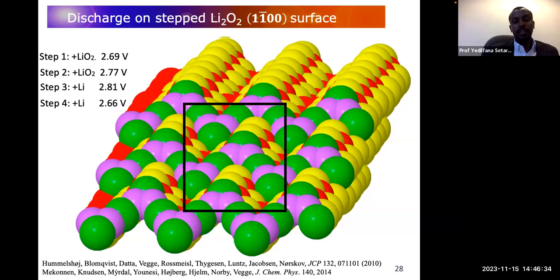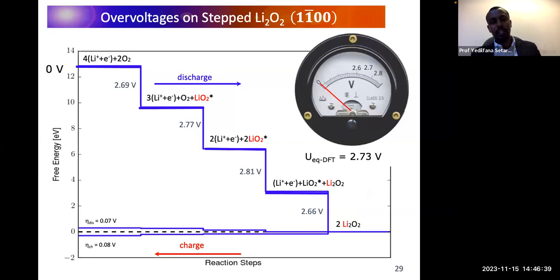Then I convert these energies into the graph of the free energy diagram. I use those energies from step 1 to step 4. And finally we see this downhill free energy diagram. Downhill tells me that we are getting energy, just spontaneously. So in absorption, you get this amount of energy in each step. The average, you sum up all, then divide by 4, then you get 2.73. This is the equilibrium potential.